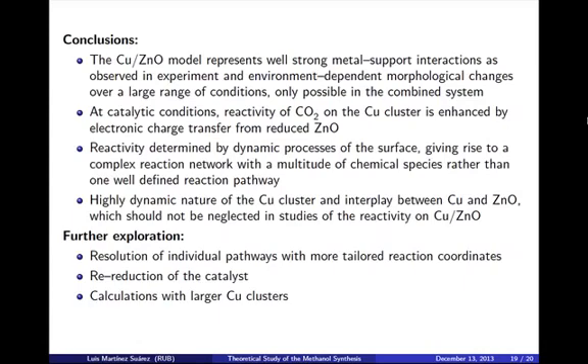After having gained this insight, further work should consider resolution of individual pathways with a more tailored set of reaction coordinates. Also, one must take care of the oxidation state of the surface — during the MD simulation, CO₂ gets reduced and thus the catalyst gets oxidized, which under realistic conditions would be immediately re-reduced. Also, small copper clusters already capture well the chemistry of the synthesis of methanol, but this should be confirmed by using clusters of real sizes with extended facets and interface.